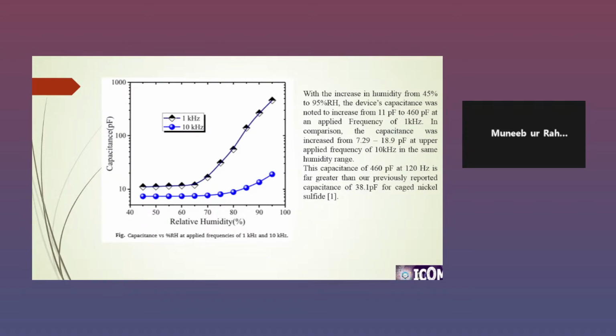Then we change the frequency to 10 kilohertz, the external applied frequency. We see that for the same humidity increase from 45% RH to 95% RH, the capacitance of the device has been dropped. Though it is increased from 7.29 picofarad to 18.9 picofarad, if we compare at 95% humidity, at 1 kilohertz and 10 kilohertz, the capacitance of the device at 1 kilohertz was 460 picofarad, which dropped to 18.9 picofarad at 95% RH.